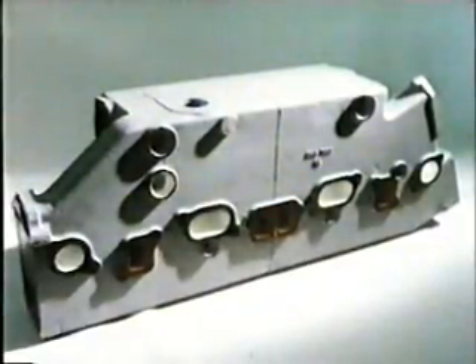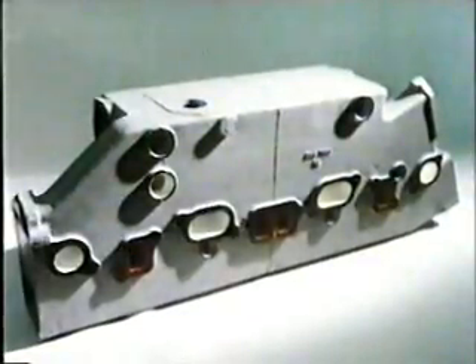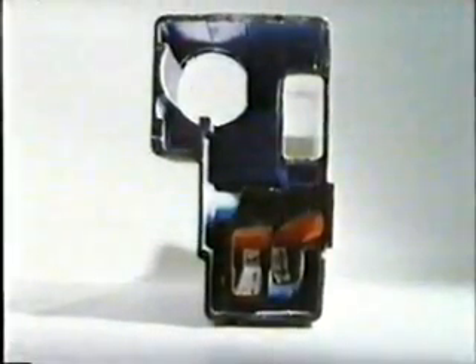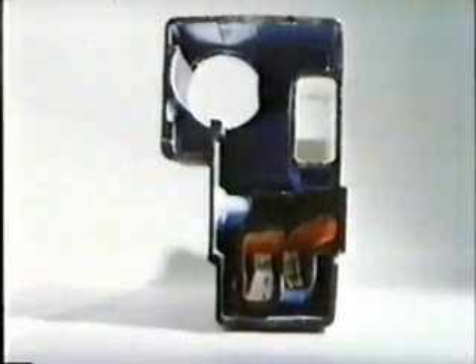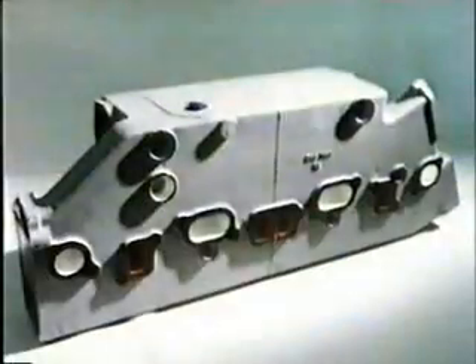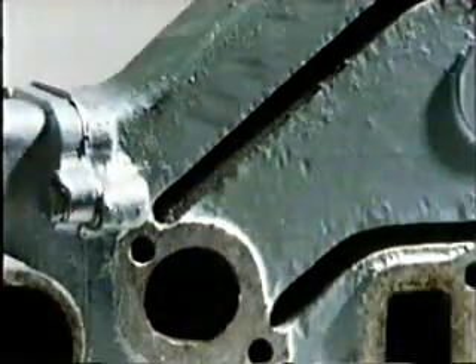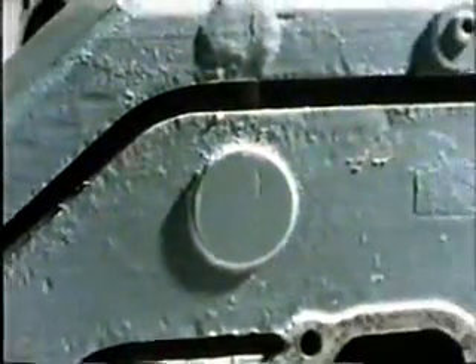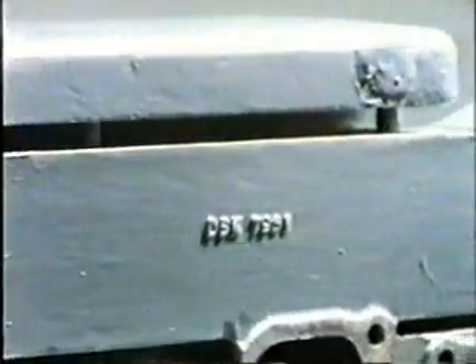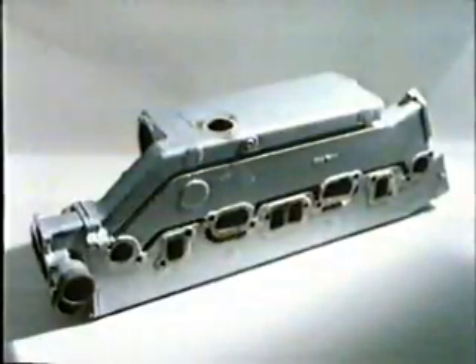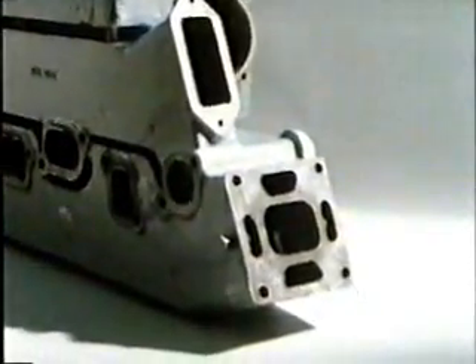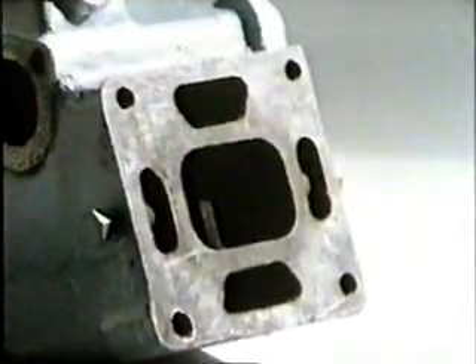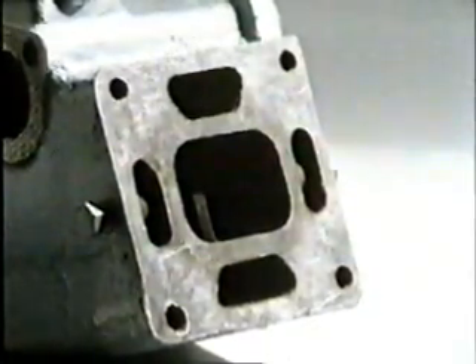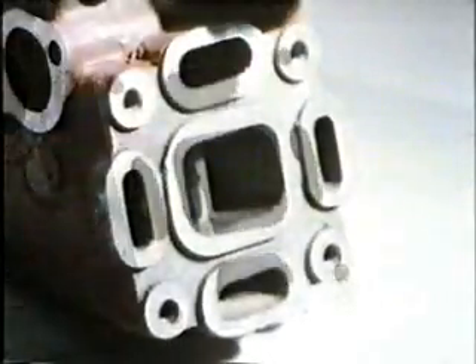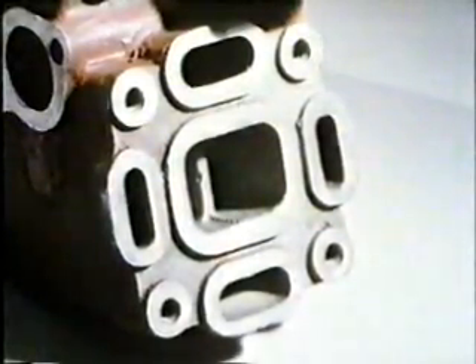The first prototype proved that the idea was valid, but there was a problem. The air entering the intercooler began to be heated as soon as it entered the system. By the time it got to the engine air intake, it was too hot. The remedy was an air gap designed into the casting to insulate the airflow from the rest of the system. Then another problem. The face where the turbocharger was fixed was found to leak. Flat surfaces are all difficult to machine perfectly flat. Flanges at the joint face reduce the error needing perfect machining.